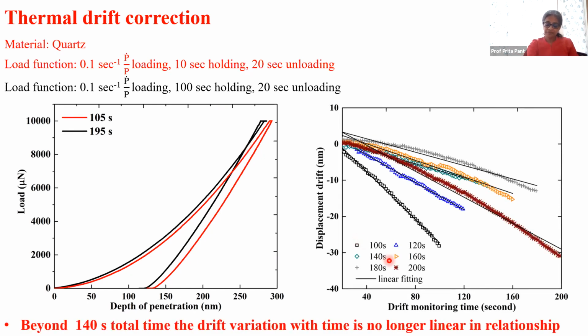So we've done a lot of studies on drift correction, and this is again displacement measurements with no applied load, and this is drift monitoring time. The black here is 100 seconds, the blue is 120 seconds, and the green is 140 seconds, and the black lines are straight lines fitted to that, mx plus c. You can see the black and blue, the green you can't see very clearly. I'm sorry about that. But here you can see the straight line fit is fine. So my original drift data that I've collected should work. I subtract that and I should get sensible results.